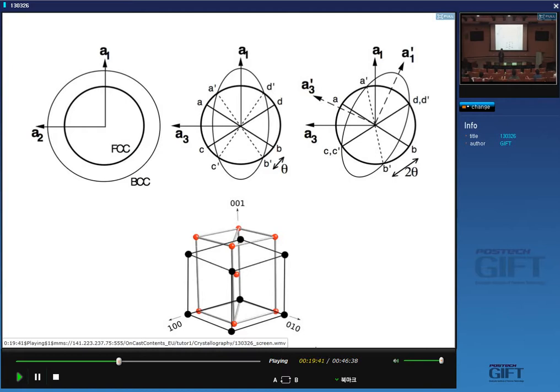So if you do the Bain strain, which is very simple, you know the distortions. You know the lattice parameter of austenite and ferrite. And then you find a rotation which will produce one coherent line between the austenite and ferrite that exactly predicts the orientation relationship. So what you observe as the orientation relationship is exactly because of the need to produce an invariant line and therefore reduce the interfacial energy between austenite and ferrite. And because the activation energy for nucleation varies with the cube of the interfacial energy, you need that coherency when the particle is small.